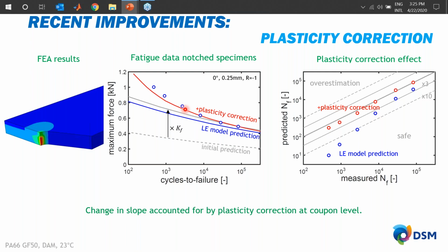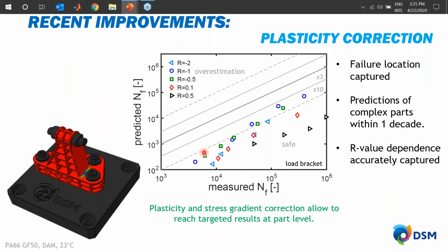And the nice thing is that if you also do this on parts, where the initial prediction was between this factor 5 to 30, actually locally this high local stress already results in yielding. So if you then compare it with the new prediction with plasticity correction, you can see that all these points shift into this factor 3 type of range. So the predictions of these complex parts are well within this decade. So we're really happy seeing this. And it also tells you that if you combine a plasticity controlled failure with stress gradient correction, you really achieve targeted results, which we set up between a factor 10.